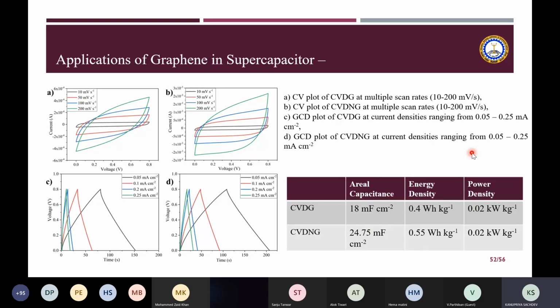These are the various plots of this doped graphene, which we tried to use as electrodes in a supercapacitor. We compared the nitrogen doped graphene with undoped graphene, and what we could find out was a significant increase in the areal capacitance. You can see very clearly, these are the CV plots of the CVD graphene, and these are the CV plots of the nitrogen doped graphene. You can see that there is a bigger area of the plots, and this gives you the voltage curves for the undoped and the doped graphene. What we see here is that the areal capacitance increases significantly. There is a slight increase in the energy density, with the power density remaining the same.